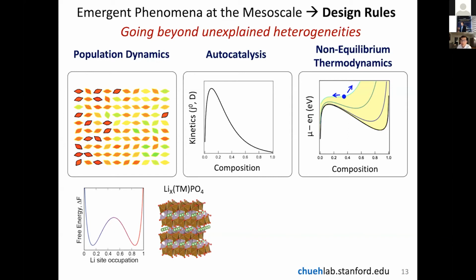This material is characterized by a very large miscibility gap. So I show here a schematic free energy diagram, so it has a usual double well. So this means that for a majority of the composition of the material, it will have a phase separation.